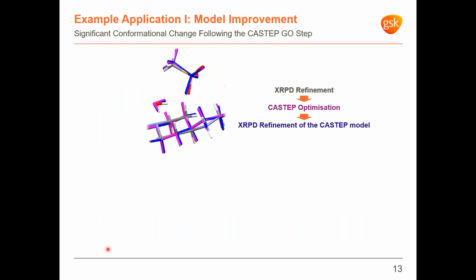Let's take now a closer look into the molecular and supramolecular aspects of the different structural models at the different steps of the process. So in this overlay, looking at the atomic color-coded model, we see the initial conformation around the protonated nitrogen, resulting in a long NHO interaction with the mesylate oxygen. After the following CASTEP optimization, we observed the flip of the nitrogen, coming now closer to the mesylate oxygen of the model in magenta. And the blue model is from the final Rietveld refinement and looks in good agreement with the one obtained from the CASTEP optimization step.